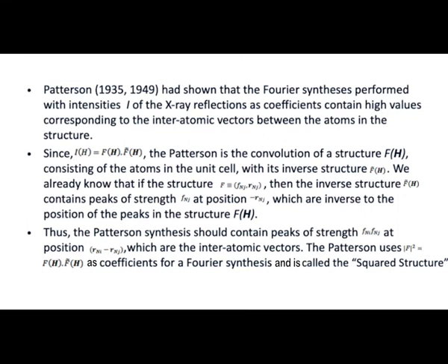But the input to the Fourier synthesis should be both the amplitude and the phase of the Bragg reflection, whereas Patterson does not require the phase of the Bragg reflection, mere intensities are enough. So that is the advantage of Patterson. Phase problem is not there, but it gives only the interatomic vectors. We have to find the individual atomic positions later. That's okay. Patterson has a lot of use in the field of macromolecular crystallography, which we will be seeing when we talk about the topic.